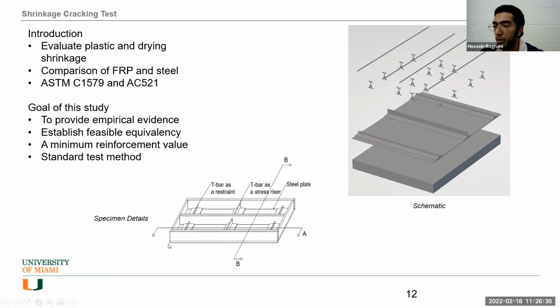Here I do not have the dimensions, but the slab is like 4 feet by 3 feet by 4 inches in depth. We introduced some restraint and a riser inside the specimen to force the concrete to crack. You know, because in shrinkage, if you let your concrete shrink, all the parts shrink together. At the end, you will not see any cracks because you do not have any stresses. You need some restraint to limit your concrete and have different shrinkages in different parts to develop the stresses. And when the stresses exceed the tensile strength of your concrete, you will see those cracks.